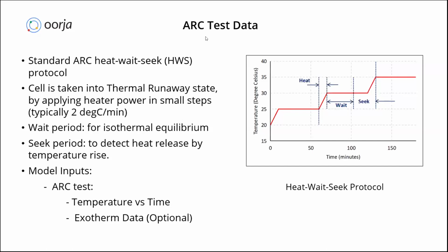So at Oorja, we use data-driven physics-based models, wherein we use the ARC test data, that is accelerated rate calorimetry test data. By using that test data, we characterize the cell for thermal runaway. That means we estimate the various parameters defining the thermal runaway in the cell itself. And once those parameters are estimated at the cell level, we build the entire pack in Oorja. Once that pack has been built, we can understand how thermal runaway initiation and propagation happens in the pack itself.